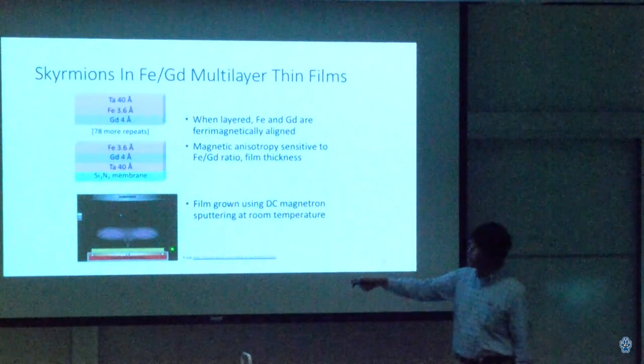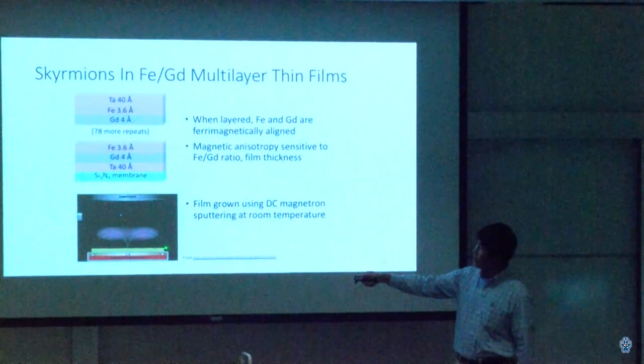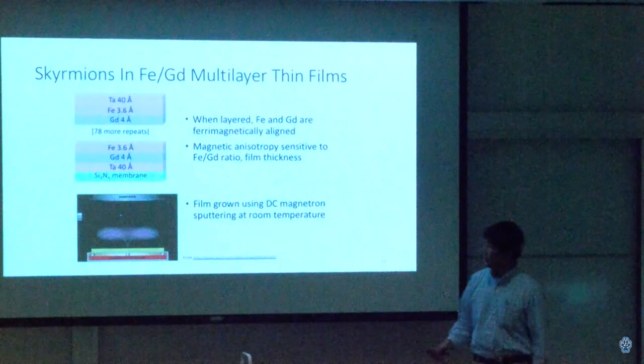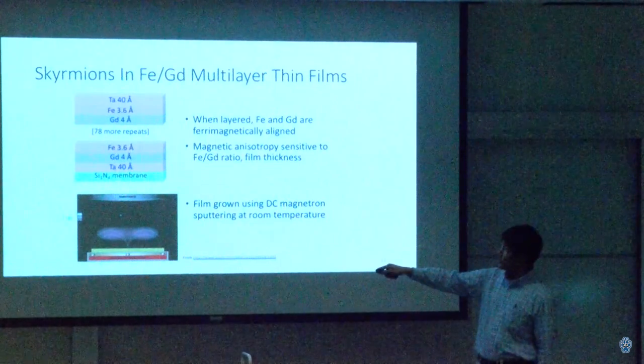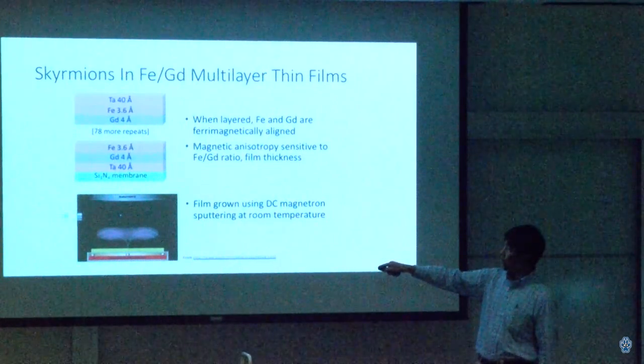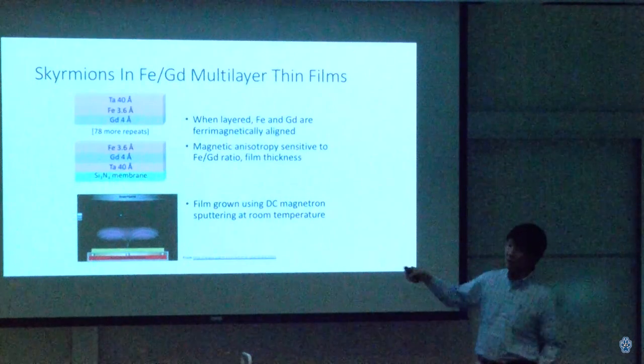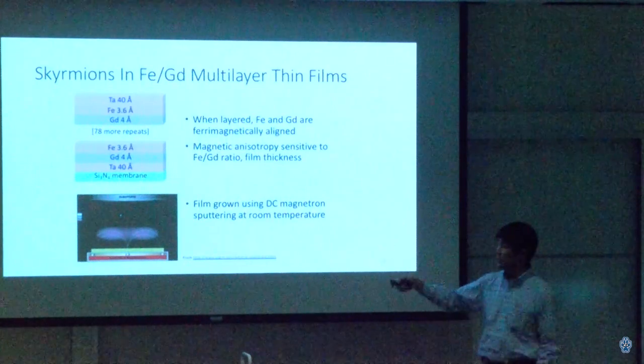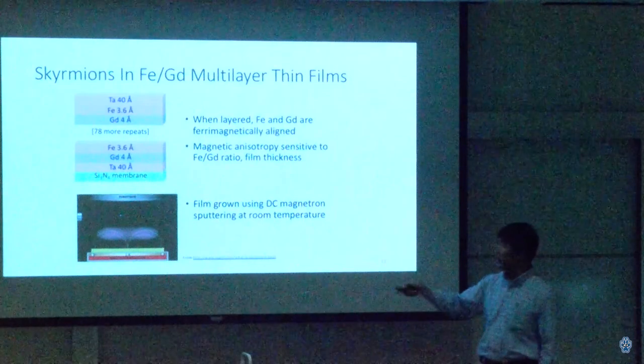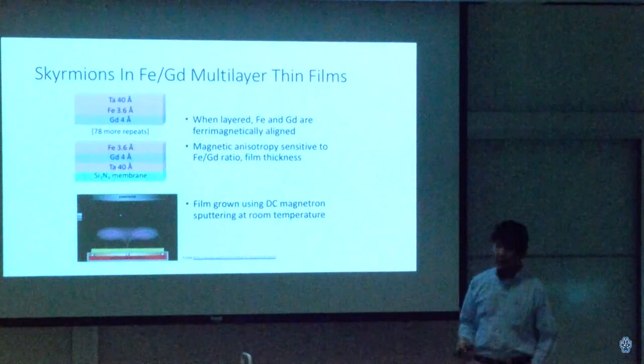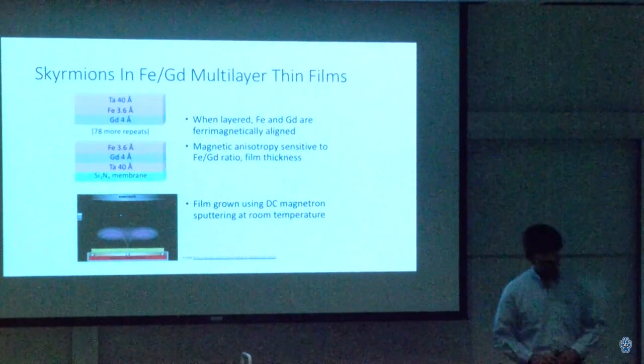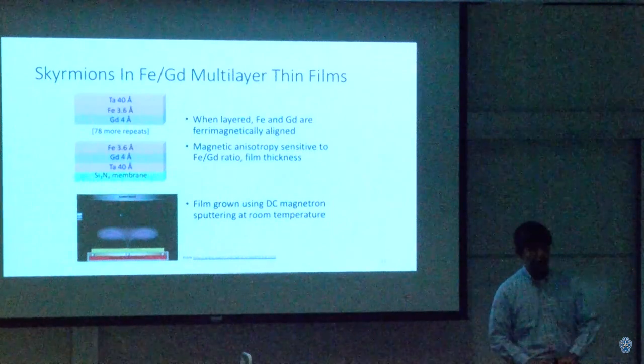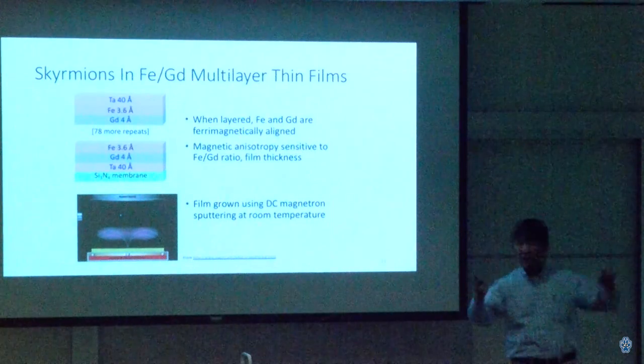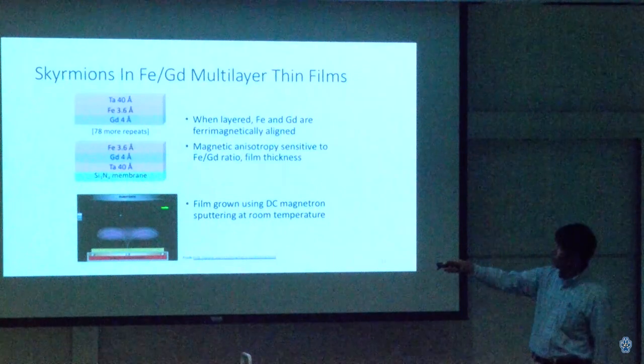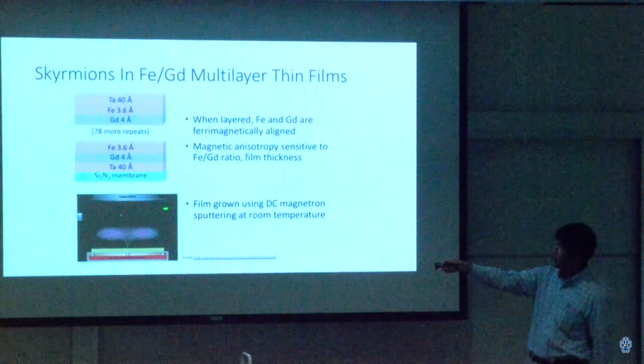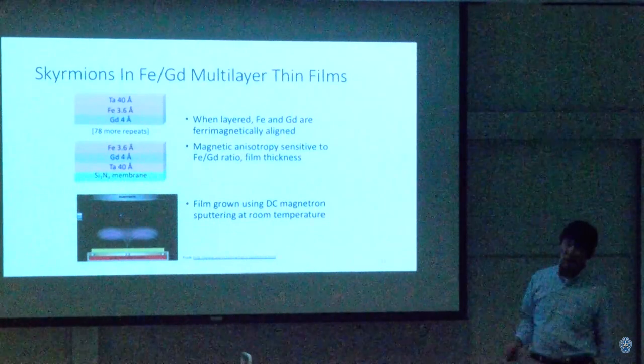What you're seeing here is a metal target. It could be iron or gadolinium. And the idea is that we want to slam individual atoms of some large atomic radius gas, like argon, into this material. When you do that, atoms and molecules from the target sputter out and then travel every which way. Some of it will end up on the so-called substrate, which is where our sample lies.